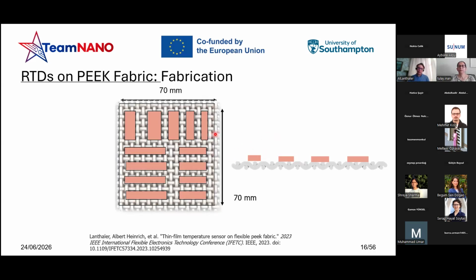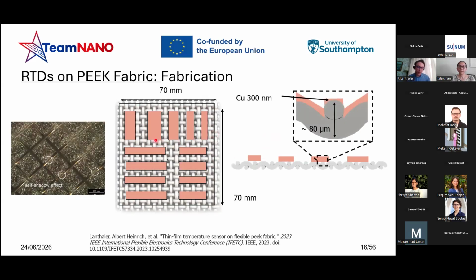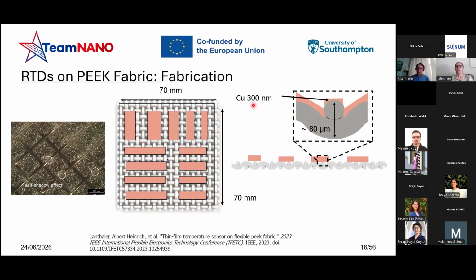Unfortunately, guess what? The device wasn't conductive at all, because, as you might guess, and having a look at this picture over here, pulling very gently the fibers from one on top of the other, we can see a self-shadowing effect between the single fibers, which is also justified by this schematic over here. If you think about it, we would like to achieve a 300 nanometer thick thin layer on an 80 micrometer substrate. How to do that? How to sort this issue out? One idea is to perform the same coating technique on the back as well, trying to achieve conductivity and continuity between the top and the bottom. And it worked pretty fine.